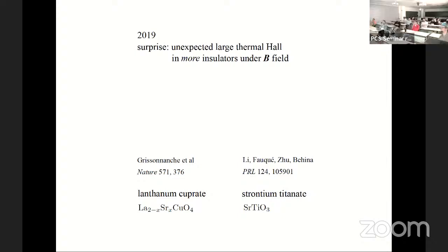Further experiments confirmed that there's really nothing unusual related to whatever emergent things in cuprates. Because in the same year, this unexpectedly large thermal Hall effect was observed in more insulators under magnetic field. In particular, Behnia's group did the experiment for strontium titanate, which is a relatively well understood, simpler material that is widely used in condensed matter. And even in there, a very large unexpected thermal Hall effect has been observed.